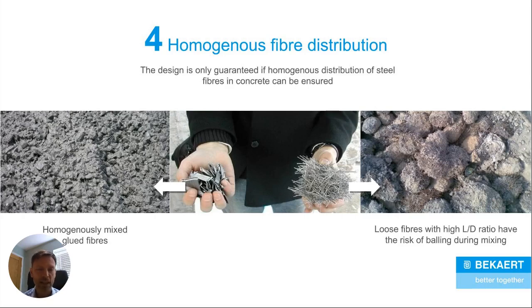The way that we make the addition of these easier is to collate them into clips using a water-soluble glue. The principle being that the fibres are added up on a simple conveyor into the concrete. As soon as the fibres hit the mix, the water in that mix breaks down the water-soluble glue, and then the fibres disperse in the concrete. So it's important to know if you use a high-performing fibre, if they are glued, they will mix a heck of a lot better.